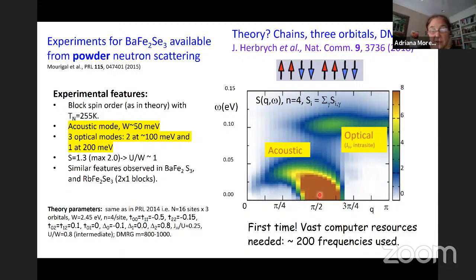It is interesting to see that the acoustic mode has a maximum at pi/2 and disperses in this direction, but there doesn't seem to be much spectral weight at higher momenta in the Brillouin zone. We believe this is because these are magnetic excitations between the blocks. When we have size-2 blocks, this effectively doubles the lattice size, from A to 2A, and when the lattice size doubles, the Brillouin zone size decreases by half. So instead of having most of the weight at the zone boundary, we have it at pi/2, which could indicate these blocks talking long range with each other.